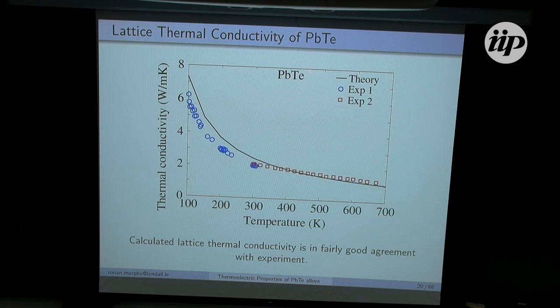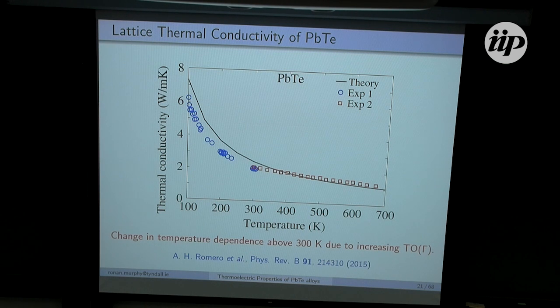Here's a function of temperature. Our calculated curve is in black, and we have 2 sets of experimental data in blue and red. For low temperatures, say 100 to 300 Kelvin, our results are about maybe 20% higher than the experiment. Now, from about 300 Kelvin upward, the results appear to be very good and agree very well, but you will notice that the temperature dependence is slightly different. So say the calculated curve goes down like this, but the experimental data points cross over. Now, this is because of what I mentioned previously about that increase of the TO mode frequency, which has a tendency to increase the thermal conductivity as you get to higher and higher temperatures. So that is something that unfortunately isn't captured by our theory, but nevertheless, as we go on, we will be able to look at trends in changes in the thermal conductivity and see what happens as we get nearer the phase transition.